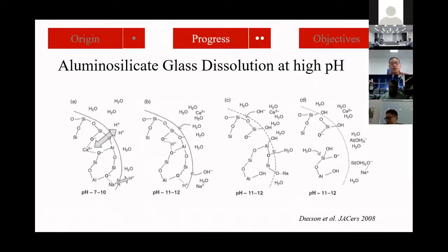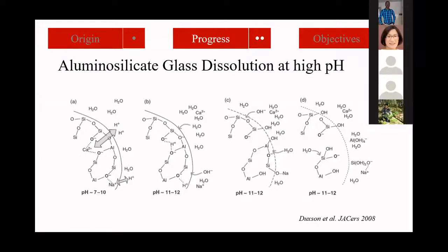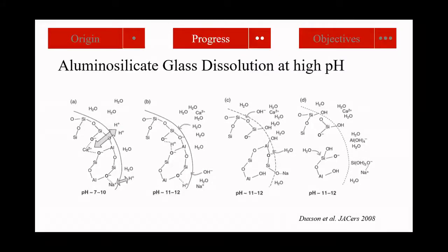Recent studies give some examples. We all know aluminosilicate dissolves at high pH, and this is just a general idea of how it dissolves in high pH solutions. First, the cations, for example potassium, exchange with hydrogen in the aqueous phase, and the water or hydroxide will attack the silicon-oxygen and aluminum-oxygen bonds, and silicate or aluminate hydrates are released from the glass into the alkaline solution, and the solution is then controlled further by the dissolution-precipitation process and forms hydrates.